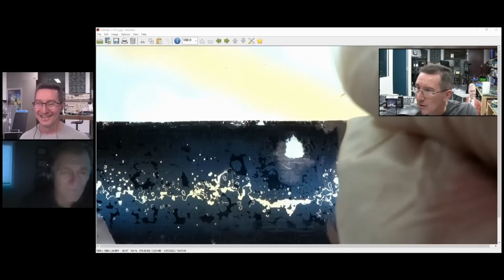Right. But it's funny. My first job within AVX was on glass dielectrics themselves, and we made thicknesses of about 1/1000th of an inch. Maybe 1.2 thousandths of an inch. And you could bend them quite effectively, maybe around a 6-inch radius or so. Wow, really? That's amazing. Yeah, glass had a lot of advantages. It was exceptionally stable. It was probably the most reliable part out there. The K factor was only approximately 8, so it's not too much.